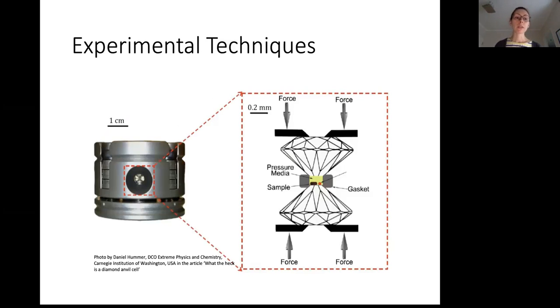So for all of our experiments, we used the diamond anvil cell, which is shown here. I'm sure many of you are familiar with this. It's a little handheld contraption, which right in the middle has two brilliantly polished diamonds, in between which you put your sample and then whatever else you want to compress along with it. So usually we use a pressure medium, which acts like a little pillow to help distribute the stresses and make the sample chamber more hydrostatic, as well as some kind of a pressure calibrant. So something whose equation of state, how it changes with pressure, we know very well, so then we can get a better idea of what pressure our sample is at.